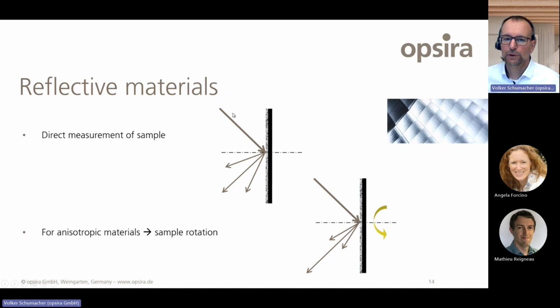The easiest one is the reflective materials. There we can use the sample directly for the measurement. We have here a sample with a surface characteristic. It's only working in reflection. Here is the scatter structure on that component, and we illuminate the sample from different directions, different angles of incidence, from a small angle of incidence to a very flat angle of incidence, and then we measure every time the hemispherical scatter in reflection. If there is some anisotropic effect, then we rotate the sample. We see it here. Here we have a wider scatter characteristic, and here is a narrower scatter characteristic when the sample is rotated. And for this, we have the sample holder, which can be rotated on the BRDF goniometer. So that is for reflective materials.